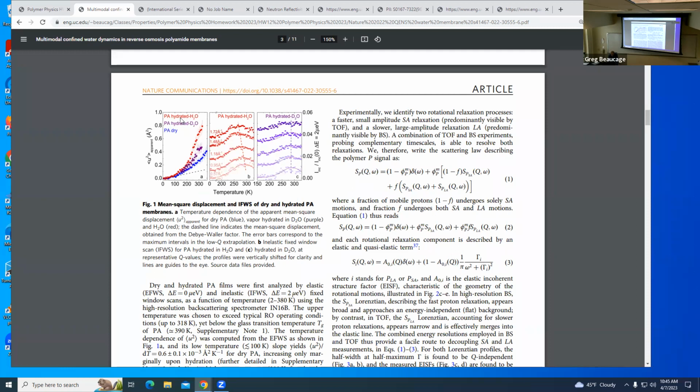And then for his polyamide hydrated with D2O, you can't see that, so that one would be just the hydrogens in the polyamide, not the water. The other one is the dry polyamide, and then soaked in water, showing how the D2O affects the motion. The last one is a combination of those two plus water moving through it. The non-Fickian, non-diffusive part is shown by the deviation from the dashed line. At really low temperatures it's just diffusive, Brownian motion, right? I think he calls it Fickian here.